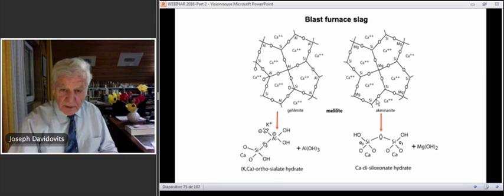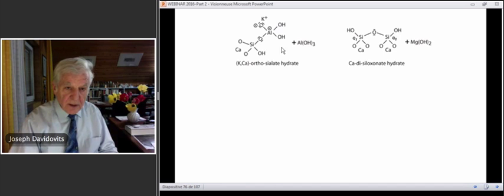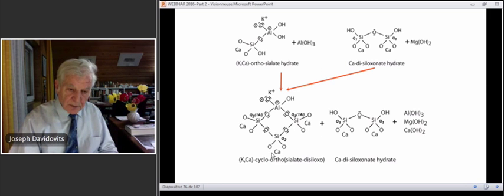For akermanite, alkalination depolymerizes the structure and provides a small molecule, calcium disiloxonate hydrate, Si-O-Si disiloxo, with calcium, and precipitation of magnesium hydroxide. This is the CSH that you find in the alkali activation of blast furnace slag. The two CSH and this one ortho-sialate hydrate interact and build the first step of geopolymerization, or the last step of alkali activation if you want.